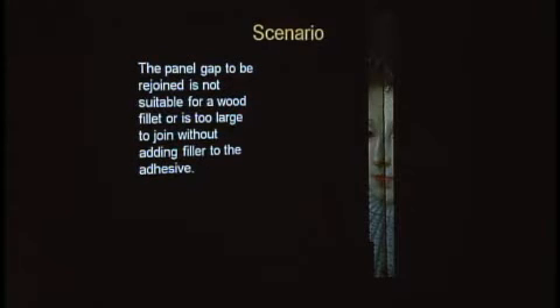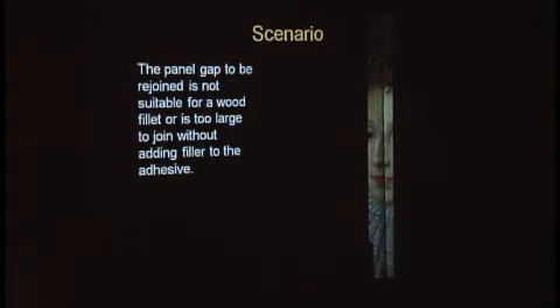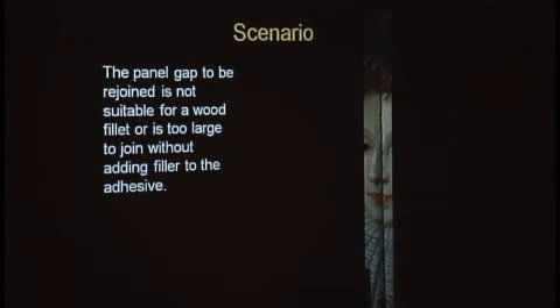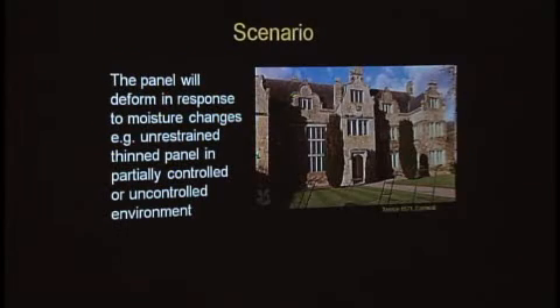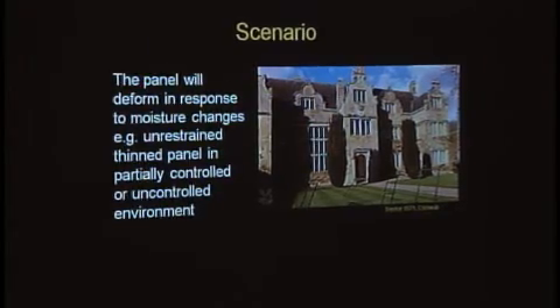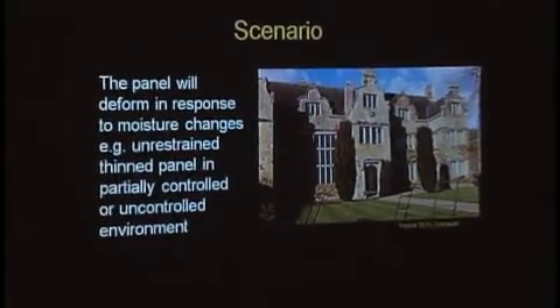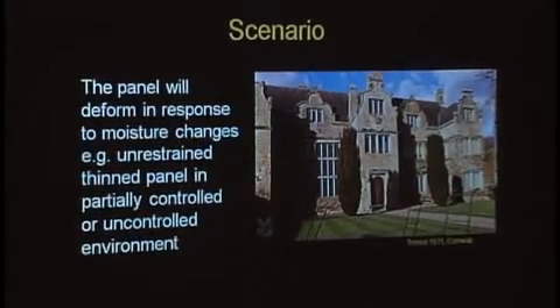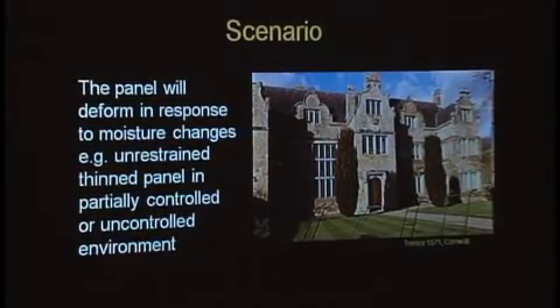So the scenario that I was particularly interested in is a gap which couldn't be rejoined without some sort of filling, whether there was room for a fillet or not. In this case, most of the time our panel splits had gaps around 2 millimetres, 3 millimetres maximum, so a gap filling adhesive was required. Our panels were also always automatically going back into uncontrolled environments where microclimate chambers weren't wanted and only some form of auxiliary glazing and sometimes backboarding was allowed.